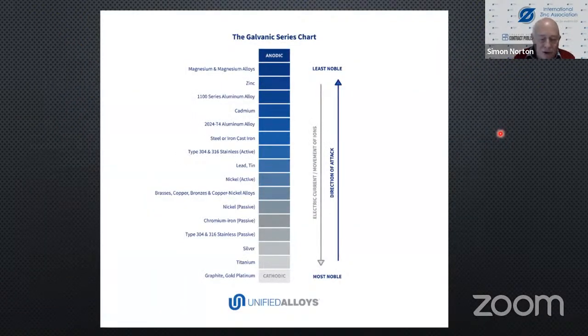Now, critical to the chemistry of zinc, and Graham Stead is going to be talking about that with respect to zinc-rich paints, and Martin Gagne with zinc thermal spray, is what we call the galvanic series. Essentially, when you coat zinc onto steel to protect it against corrosion, what you're actually doing is you sacrifice the zinc and you protect the steel. The reason, or how it works, is that the zinc forms an anode and is slowly eaten away and lost. And therefore, the thickness of the zinc coating is what's critical to your corrosion protection.